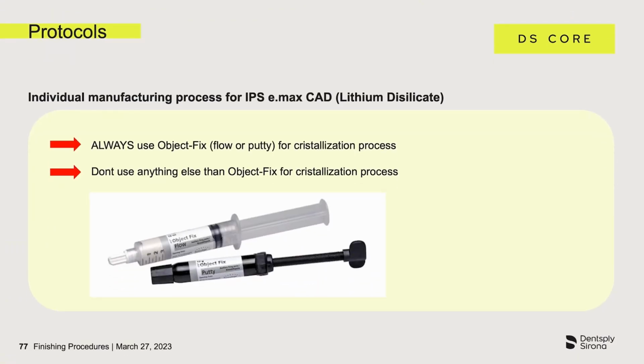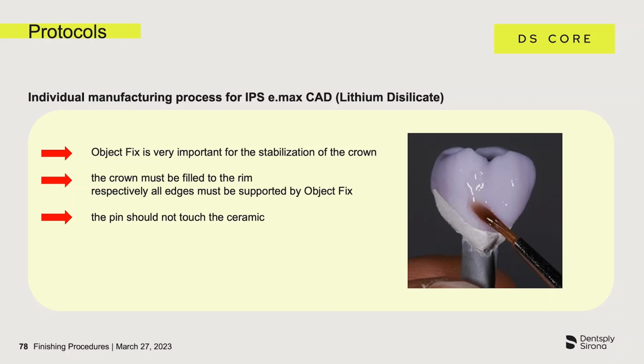It is of great importance that for the crystallization firing, when the restoration is still blue, Object Fix should be used exclusively for this stabilization. The use is mandatory and all margins must be supported. This means that Object Fix must really be applied over the entire inner surface and completely fill it up to the edges. It should also not protrude beyond the margins, but it should be flush with the edges. Object Fix has an important meaning because it stabilizes the restoration during the crystallization process in the kiln.